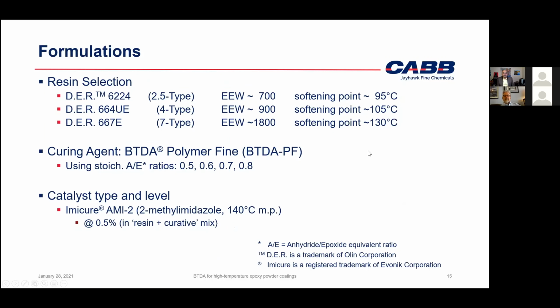Kevin, want to describe our formulation selections, please? Yeah, and I mentioned we have a survey of different molecular weight, different equivalent weight bisphenol A type epoxy resins. Kind of about as low as you can go. You go a little bit lower than this, but the lowest melt viscosity is going to be around a 2.5 type, and it's basically for storage stability issues. But yeah, we started with a 2.5 type, very common in the industry. 4 type, it's a workhorse, especially for functional type coatings, where relatively high film builds are necessary. And then we also did, I wouldn't say an outlier, but it's about as high as we go in molecular weight. It's a 7 type, and with this molecule, you're going to be looking at a fairly high molecular weight.